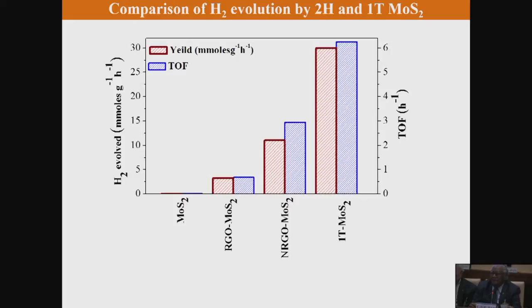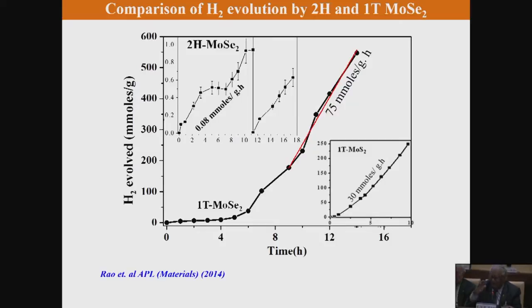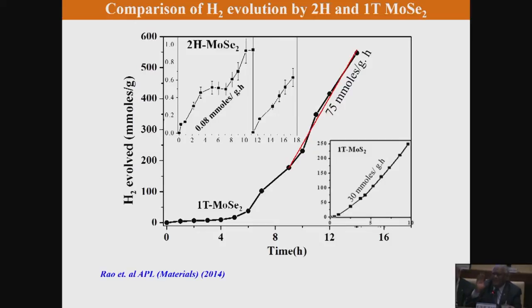This kind of situation was very interesting. My theoretical friends calculated that MoSe2 in 1T form would be even superior to 1T-MoS2. When we did that, we could get 75 millimoles of hydrogen per gram per hour, which is in fact one of the highest yields ever found in a material using 1T-MoSe2. There are other practical problems such as stability of these 1T phases, but the main thing is we have been able to produce these results experimentally.